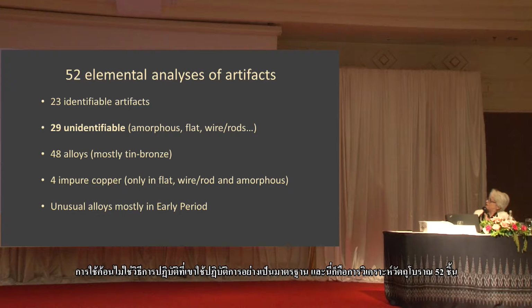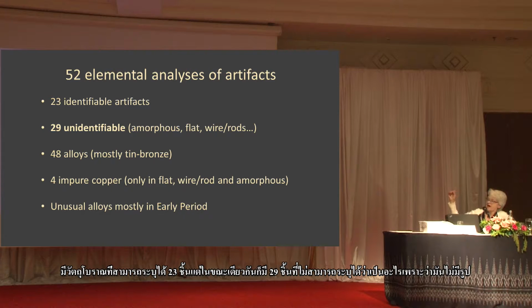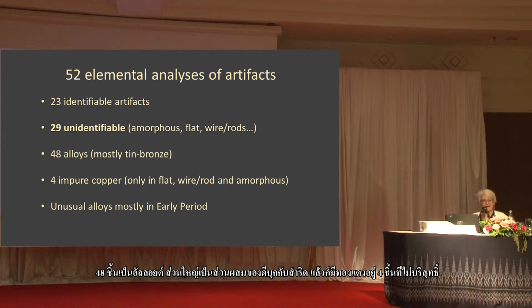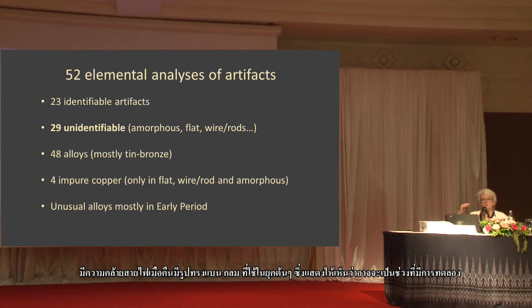Okay, so the 52 elemental analyses of artifacts: we included a little less than half of the identified artifacts, but 29 of the unidentified, including the amorphous, the flat, the wire, the rods. Of the 52, 48 were alloys, mostly tin bronze. So again, that's very significant, and the significance of this will be clearer in a slide or two. 4 were impure copper. Impure copper might have some trace elements, but they're less than 2%. So the elements might have gotten in there in ways other than a deliberate alloy.